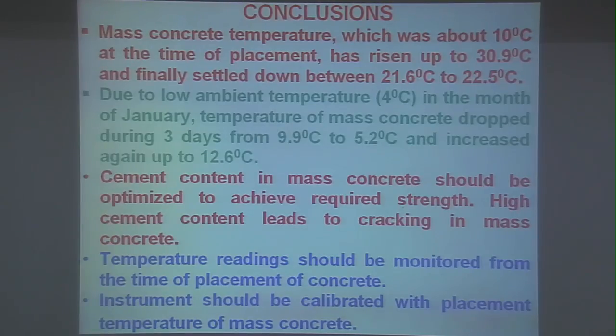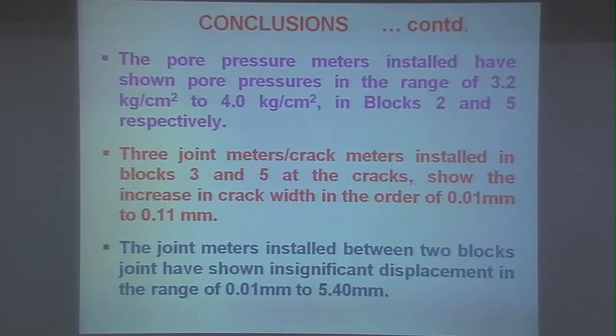So the conclusion of my work is that we could reduce this cement content in the mass concrete, and cement content in mass concrete should be optimized to achieve required strength, and high cement content leads to cracking in the mass concrete. Temperature reading should be monitored from the time of placement of the concrete so that you can have the calibration of the instrument also.